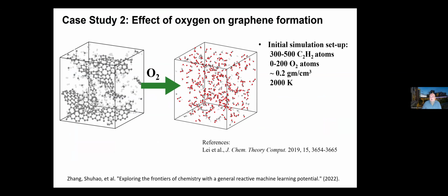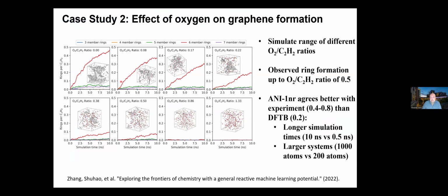Now, in parallel, you can look for more interesting applications in kinetics. So, for example, oxidation of graphite, of graphene. There is a known experiment and other simulations that, if you do a simulation of a mixture of acetylene with oxygen, depending on the ratio, the amount and type of these carbonaceous compounds would vary. And it makes sense, because the more oxygen you have, the higher oxidation you would observe. So we were able to run the simulations for different ratios between acetylene and oxygen, and essentially be able to predict the observed ratio for different concentrations and verify the experiment.